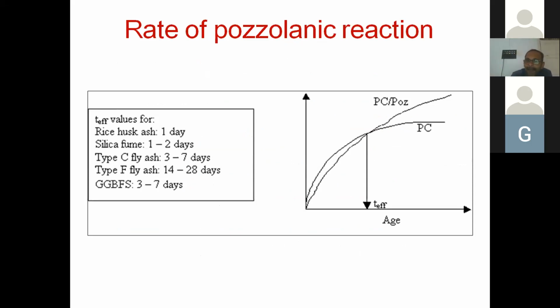When you are adding the pozzolanic material, there is only one drawback: first the calcium hydroxide has to form from the reaction of water with cement. Then that calcium hydroxide will react with the mineral admixture. So these reactions are a little slow. But how much lag there will be depends upon which type of admixture you are using. If you are using rice husk ash, it will take only 1 day. For silica fume, only 1 to 2 days. For class C fly ash, it's 3 to 7 days. For class F fly ash, 14 to 28 days. For slag, it is 3 to 7 days.